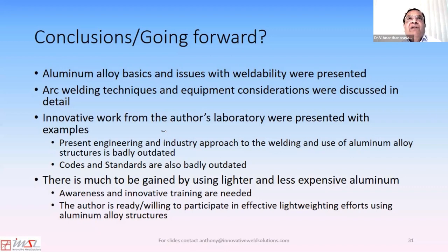If you look at the structural welding code for aluminum, when you qualify a welder to do a TIG weld or a MIG weld, you are not asking him to check the strength of the weld. You're asking him to check the cross section, so you know that there is good wetting and good fusion. And you're asking him to do a guided bend test, so you know there is good bend ductility without cracking. So those are the things you can ensure by welding a heat-treatable alloy with any kind of welding, arc welding, spot welding, or even friction stir welding.